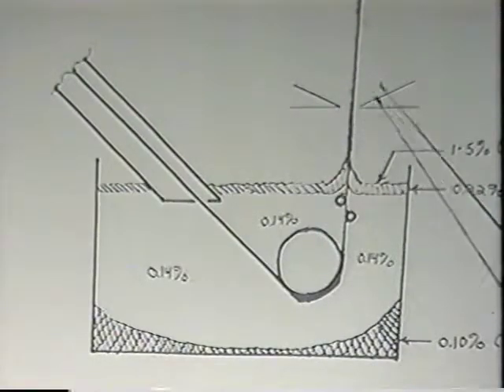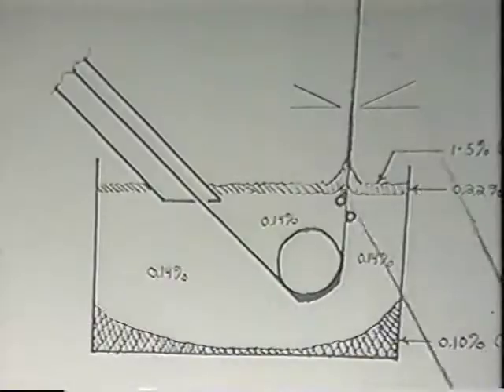So we have to blow off the excess zinc. And we do that with what we call air knives, or we happen to use nitrogen most of the time. Some people use air, some people use steam, some people use nitrogen. They all pretty much do the same thing, which is to blow off the excess zinc so you get a nice clean strip going all the way across at the proper coating weight.